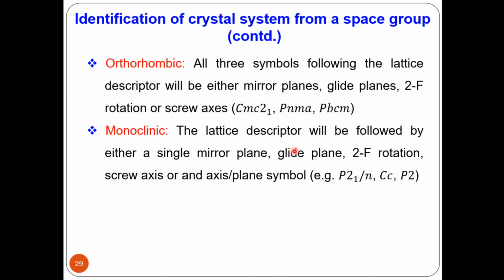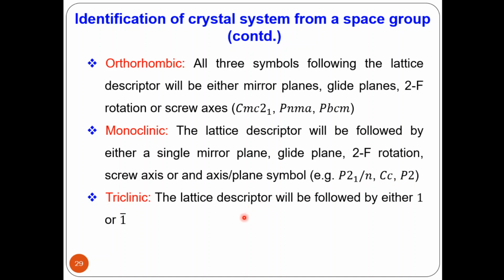For the monoclinic, following the lattice descriptor, we will be having a mirror plane, a glide plane, or a 2-fold rotation axis or plane symbol, for instance 2_1, which is the screw axis, and n, okay, a glide plane, and then following the lattice descriptor, a glide plane, and a 2-fold axis of symmetry. For the triclinic, we can have 1 or 1 bar.